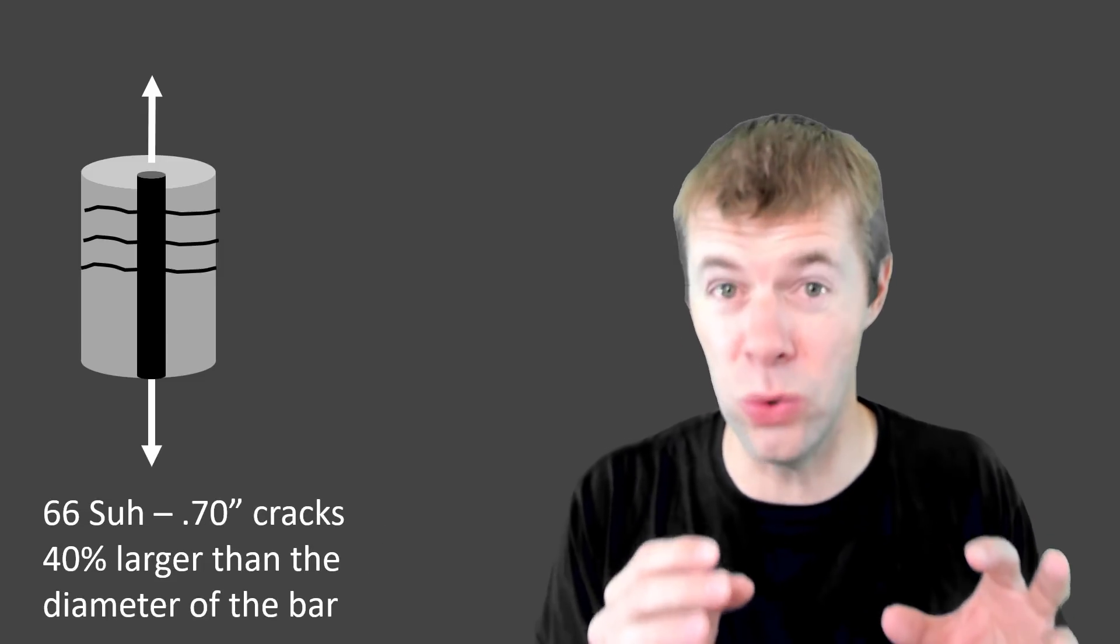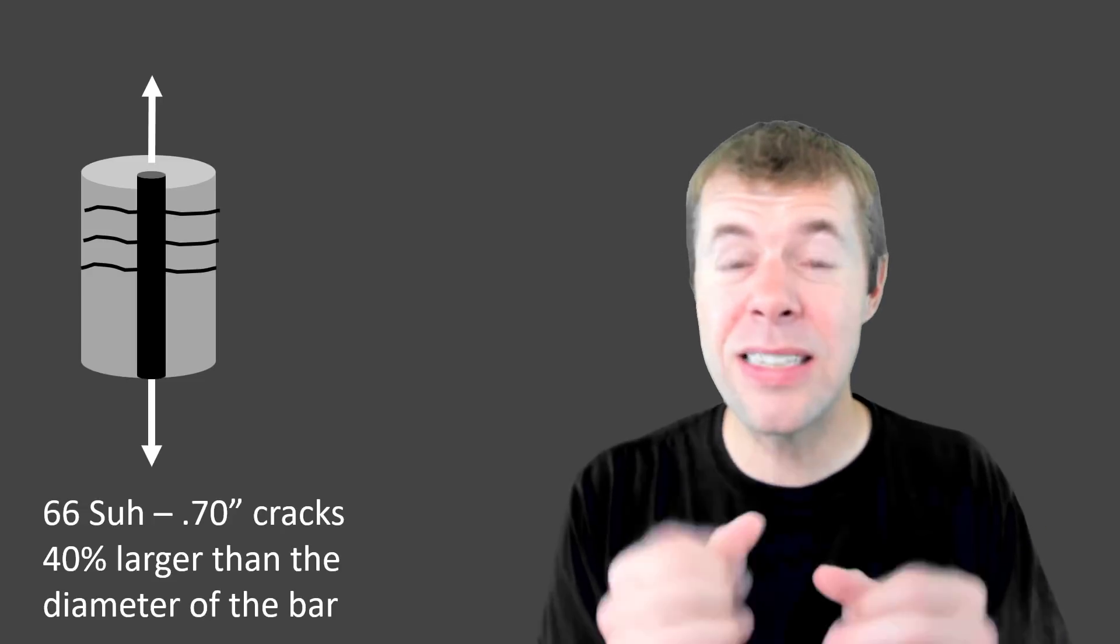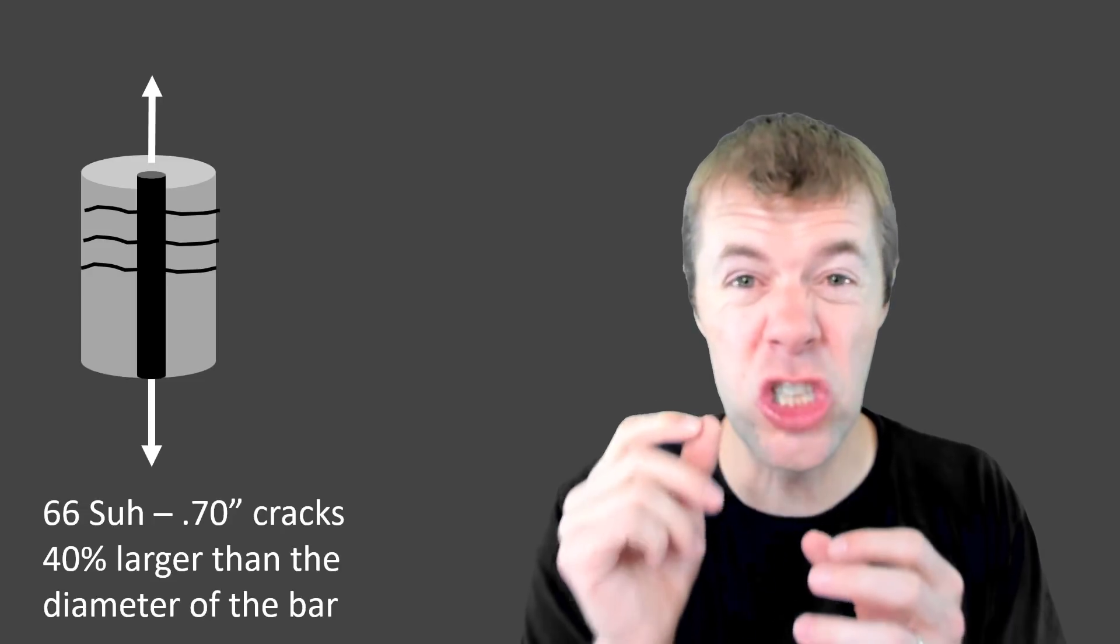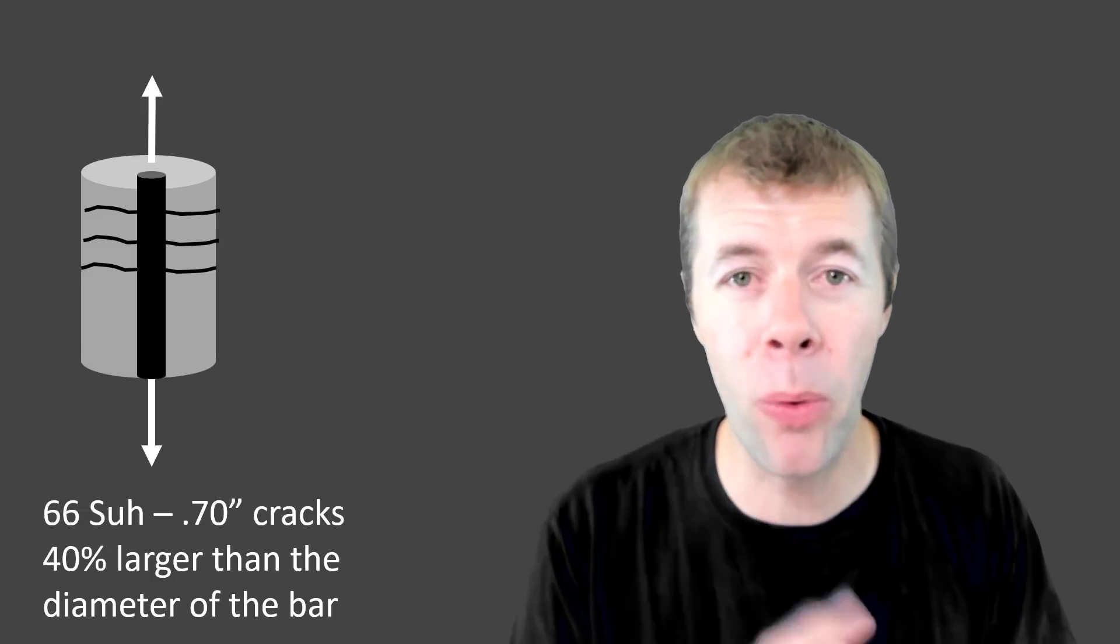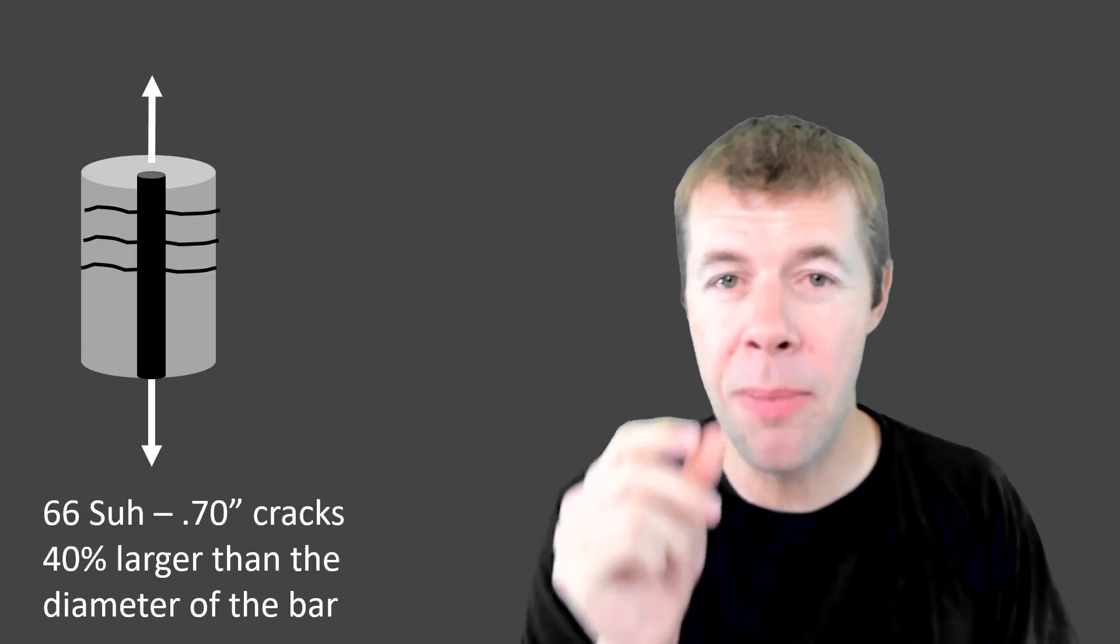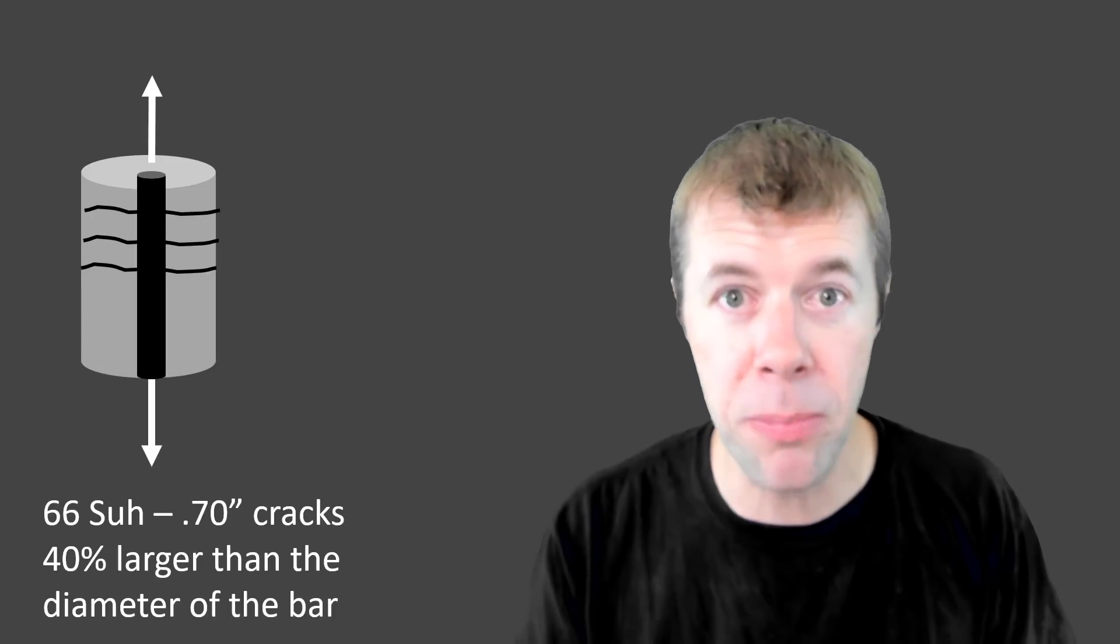And once I get to 66 ksi, that rebar is just about to break. It will break at any second. And the crack is about 0.7 inches. That is about 40% of the diameter of the rebar.